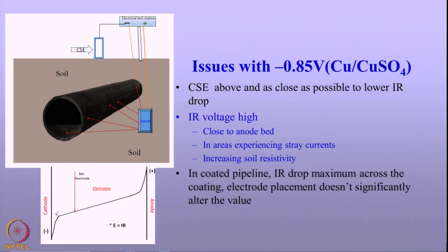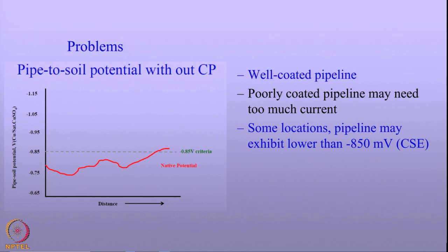If the pipeline is well coated, you would notice that because of the resistance offered by the coating, the IR drop lies very steeply between the coating and the metal surface. Compared to that drop, the soil resistance is significantly less. So, the role of IR drop becomes less in well coated pipelines. In order to overcome this particular problem, we go to the next technique. Before you go to the next technique, I would like to